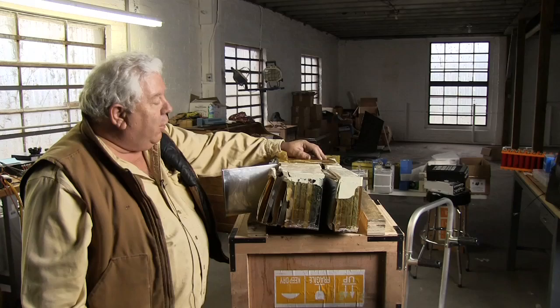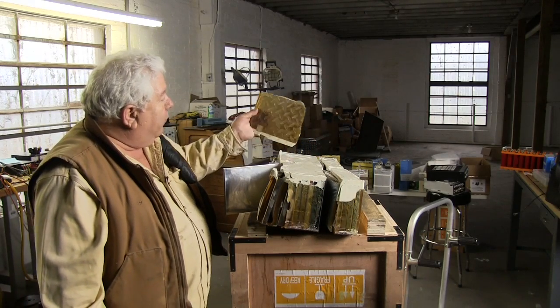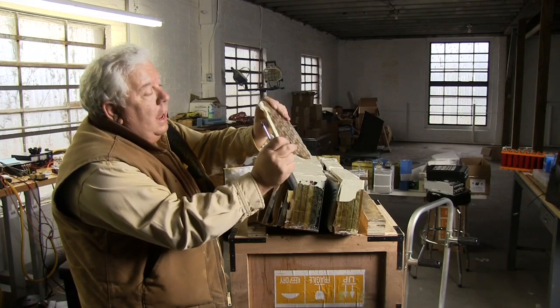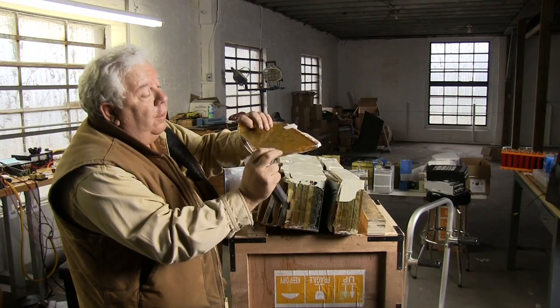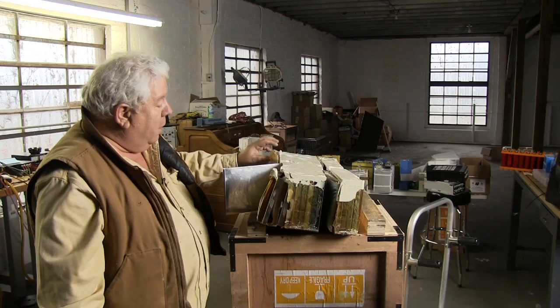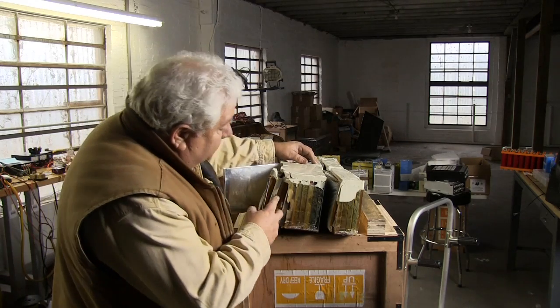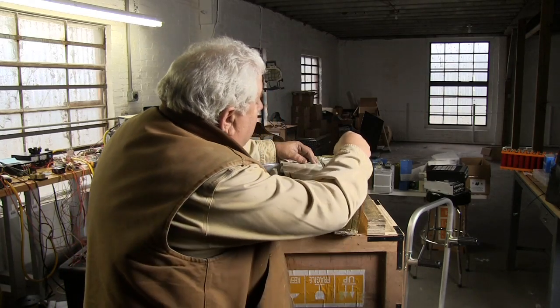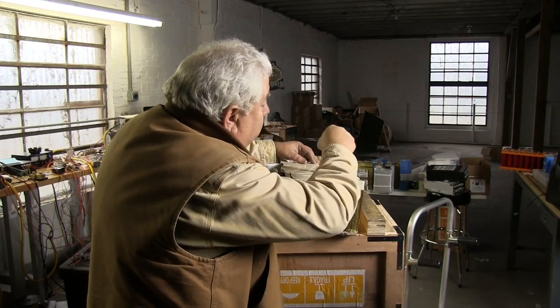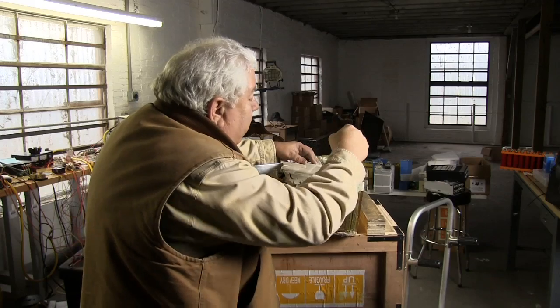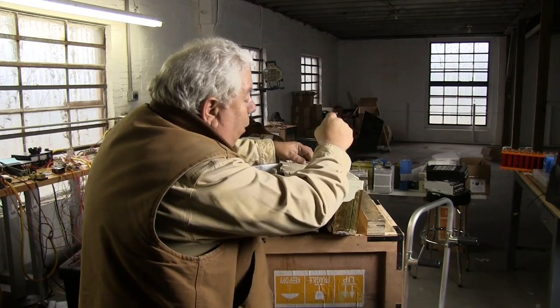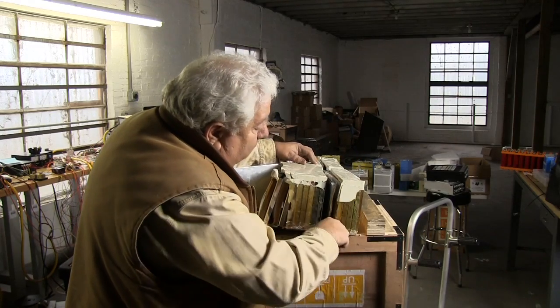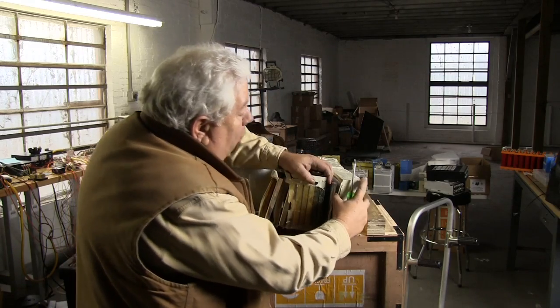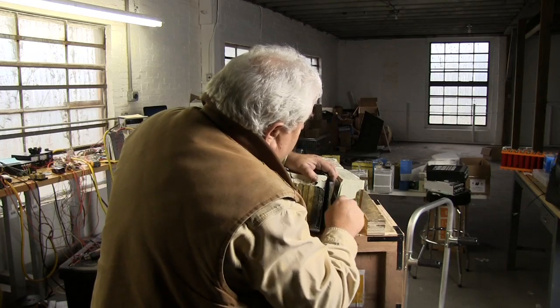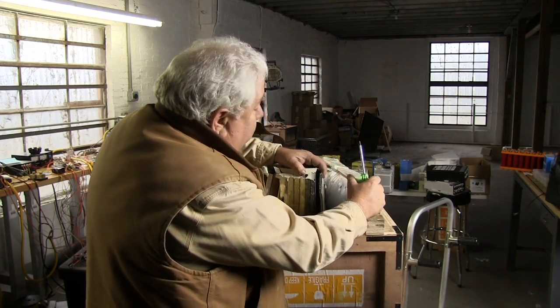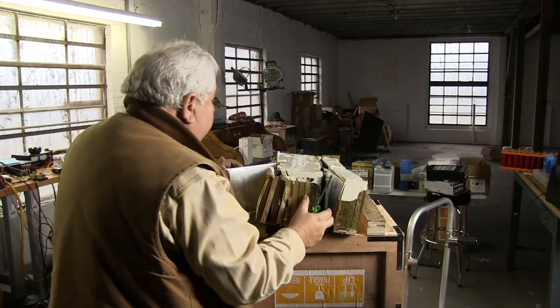And I tested this pack once it was assembled to 77.5 amp hours. It was actually very good, I thought, for a 4-cell pack. This is the resin. It's quite hard yet, a little bit flexible, but quite hard for something that thin. And this just split it wide open in a couple of places, down here and here. And it did it by a very strong pack swelling process, and the escape that you could detect by smell very easily of electrolyte, which also ran out on the ground. I mean, there wasn't any question about this. And this, my golly, it's going to come apart for us.